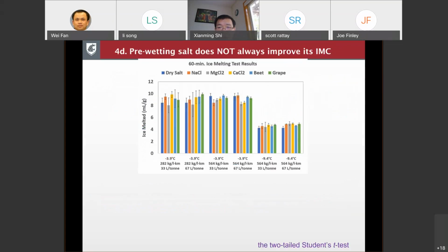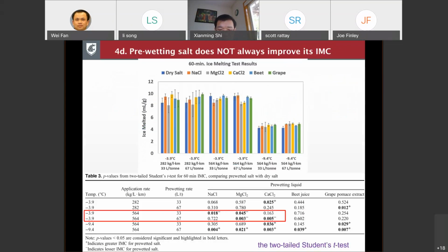Now, the interesting thing is that the pre-wetted salt actually doesn't always improve the ice melting capacity. For instance, we did some statistical analysis, this two-tailed student t-test. As you can see in this scenario, we're looking at a warmer temperature, 25 degrees Fahrenheit or minus 3.9 degrees Celsius, and 2,000 pounds per lane-mile, which is a high application rate. And you are seeing some negative numbers indicating lesser ice melting capacity for pre-wet salt.